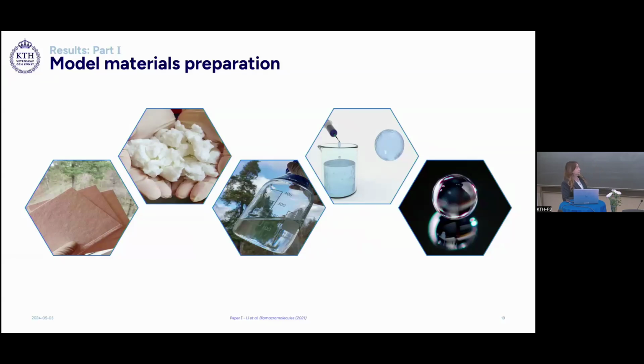The regenerated cellulose beads are prepared by dissolving pulp fibers into DMAC and lithium chloride, and then precipitating the dissolved solution into a non-solvent. And in our case, we are using ethanol, creating these gel beads, which are then washed thoroughly with water to remove any presence of the solvent.